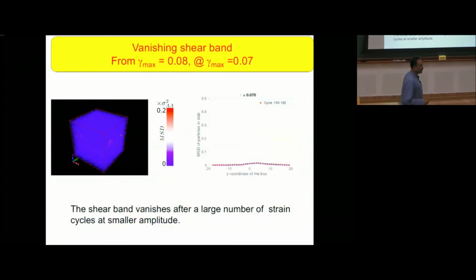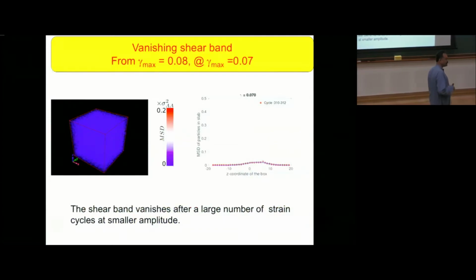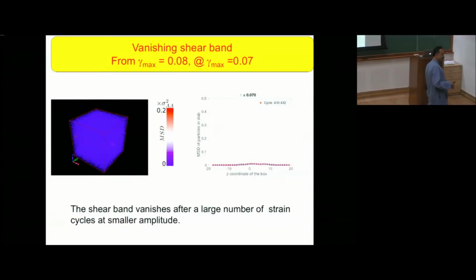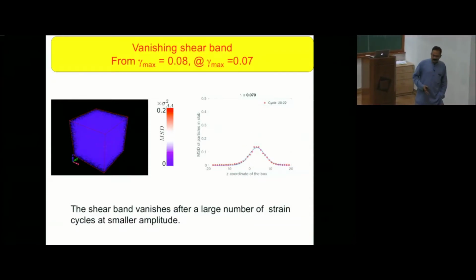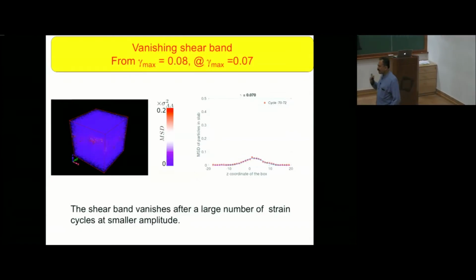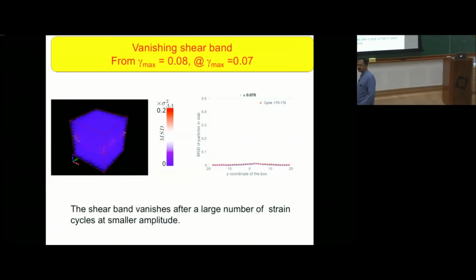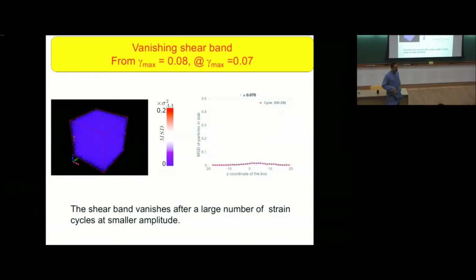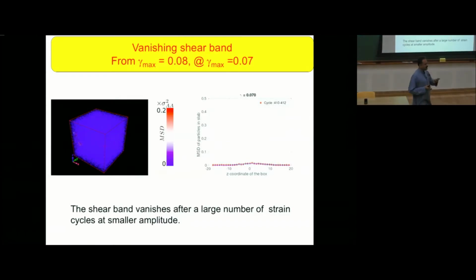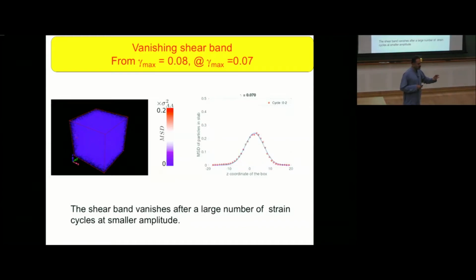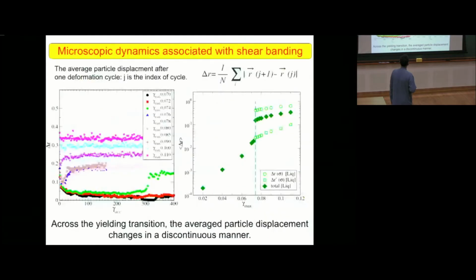This is something very interesting. I take a system which is shear banded, and I decrease the amplitude of cyclic loading, and what you find is that the shear bands actually anneal out, okay? So even in these systems where there's a lot of history dependence and so on, there seems to be a fairly unique state that the system will go to under cyclic deformation, which is interesting.